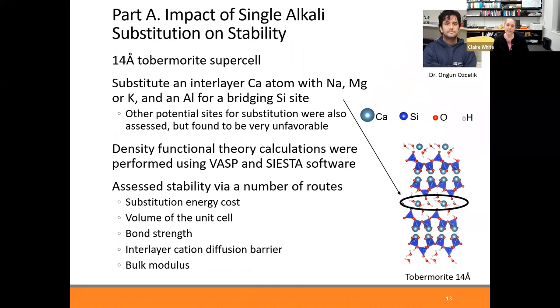So what we did in this study was we substituted the calcium atom in the interlayer with different atoms. And also we looked at the change in the thermodynamics of the system when we put aluminium in on one of those bridging sites for the silicon. We also assessed other potential substitution sites, especially for the sodium and potassium, but they were found to be very unfavorable. These calculations were done using plane wave calculations, specifically VASP, and also the Siesta software. And from these calculations, we can get a variety of properties of the crystal, such as what's the substitution energy cost when you replace, say, a calcium for a sodium? Does that change the overall volume of the system? Does it change bond strength? Can the cations diffuse around more easily? And there's other properties as well.